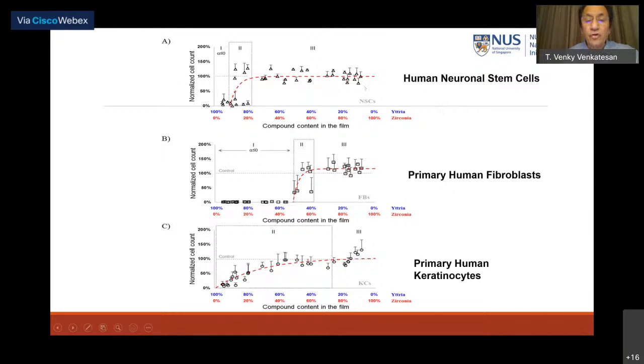So for example, on the zirconia-rich surface, the neuronal stem cells grow very beautifully, but when it becomes yttrium-rich, nothing grows on that surface, okay? Similarly, in the fibroblast case, at about the 50% point, nothing grows on the yttrium and zirconia combination. But the moment the yttrium composition falls below 50%, the growth really starts rapidly. So this gives us a clue as to how we can localize neurons at a specific spot on a given surface, because we'll take a surface covered with yttrium oxide, and only where we want to grow the cell, we put the zirconium oxide, and hopefully the neural cell will go only where the encouraging area is, right?